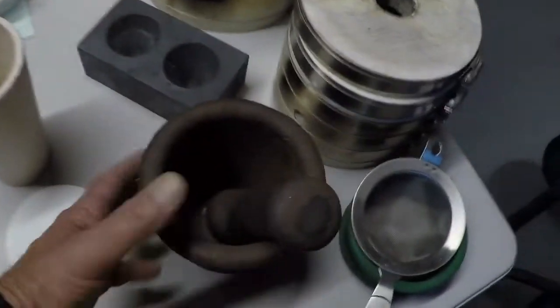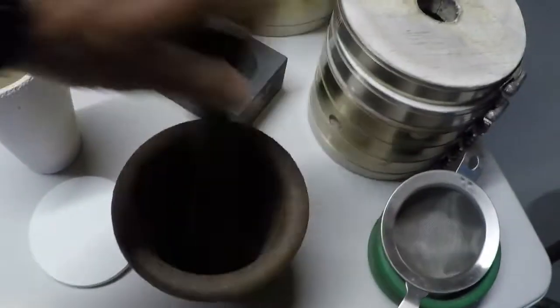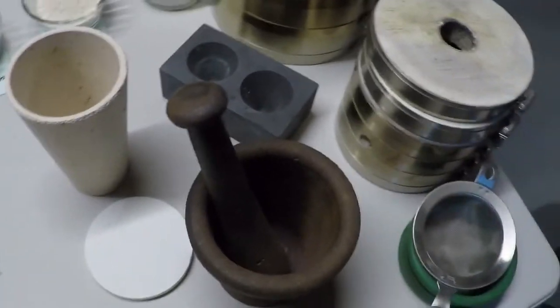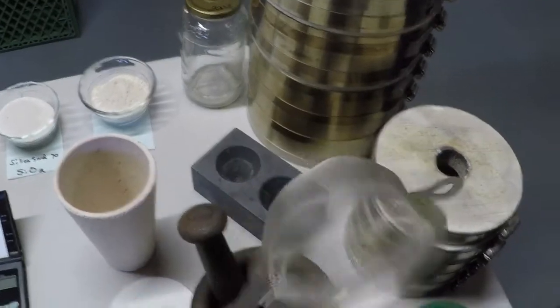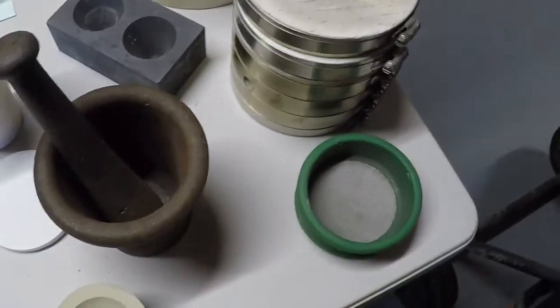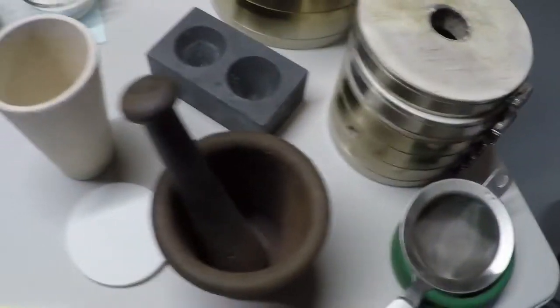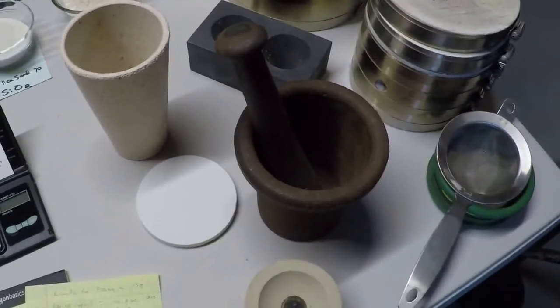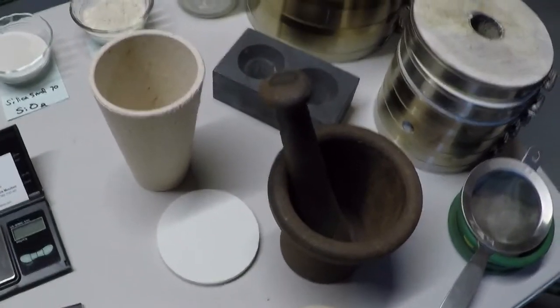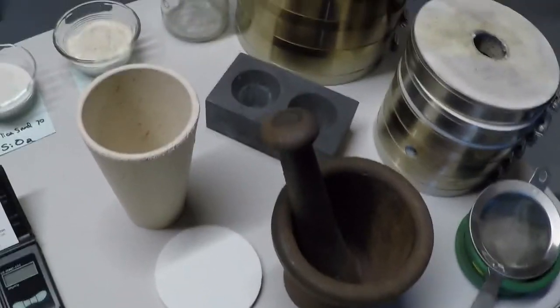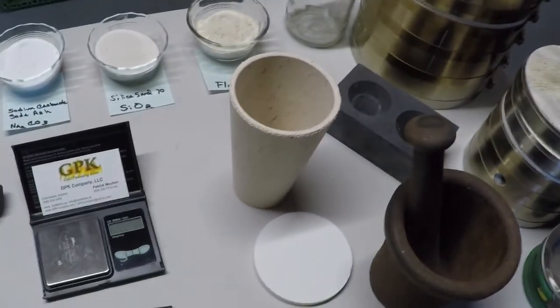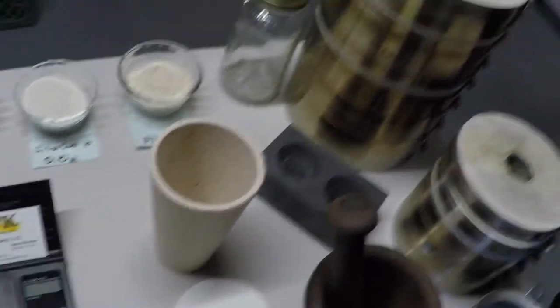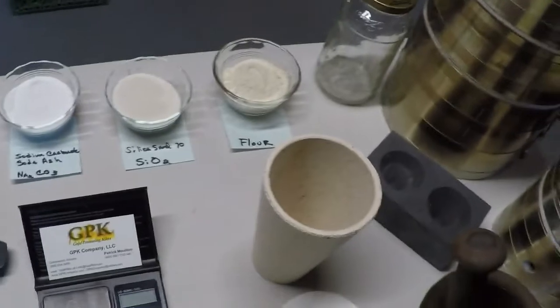using a litharge flux. I took our ore samples and I went over here and I used this mortar and pestle right here, and I ground our ore sample down to where it goes through this screen right here. This screen's about a 50 mesh. I ground it up to where 100% of it went through that 50 mesh screen. You want it as fine as you can. If you were doing a fire assay, typically they go to 100 mesh, but that's not where we're at with this little setup.